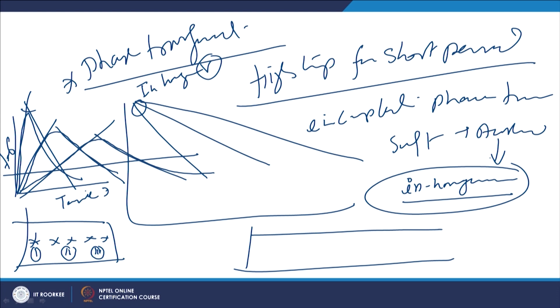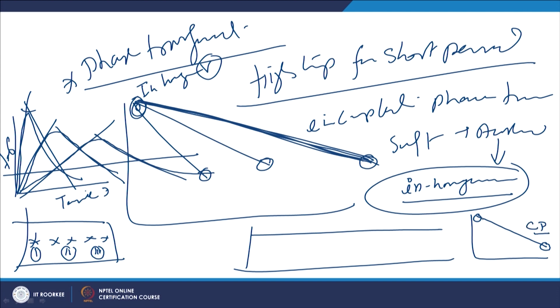So, there are two aspects: the formation of inhomogeneous austenite, and, as per the distance away from the fusion boundary, the cooling rates will be changing. The point at the largest distance away from the fusion boundary will experience a low cooling rate as compared to those closer to the fusion boundary, and accordingly the austenite will transform into different phases. Say one which is cooled very slowly will lead to the formation of coarse pearlite. Then one which is cooled at a higher rate will lead to fine pearlite. A further higher cooling rate may lead to the formation of fine pearlite and martensite. A still higher cooling rate may lead to the formation of complete martensite.